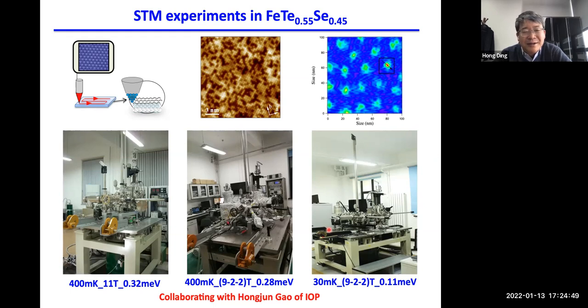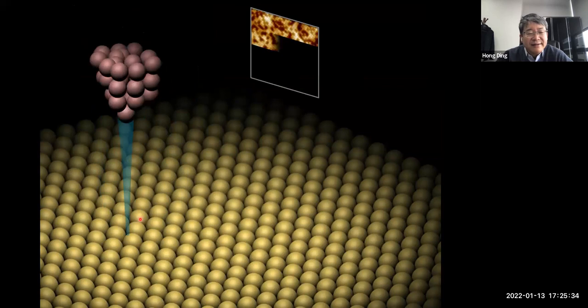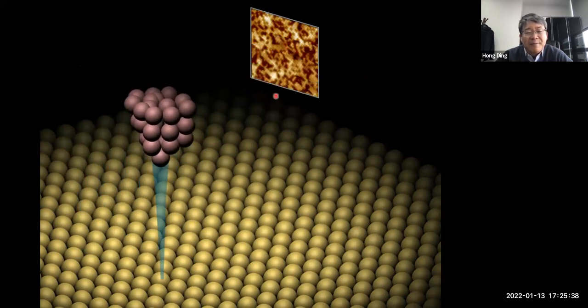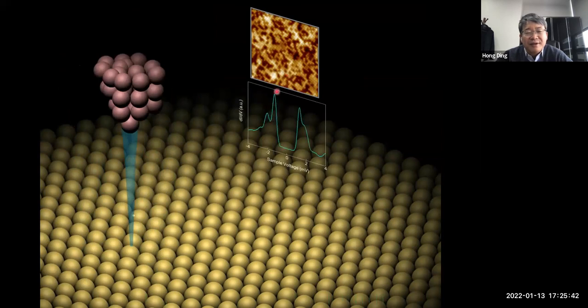So nevertheless, we went on to do the STM experiment. We collaborated with Hongjun Gao's group in IOP, since my group had no STM at that time. Now I do have an STM, we have more STMs right now. So we used one of his STMs with low temperature, 400 millikelvin, a magnetic field, and relatively good energy resolution. Later on, he got another even lower temperature STM with higher resolution. So we do the experiment, and here I show the cartoon. We scan and obtain this surface image, and we do dI/dV to see the superconducting gap.